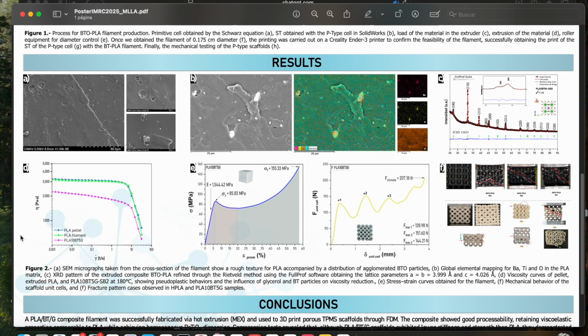The implications are that composition and architecture can be co-designed to target controlled failure in porous structures. For biomedical scaffolds, lightweight cores, or impact mitigation components, the PLA BTG TPMS delivers a practical balance: printability at low cost, tunable compliance, and enhanced energy absorption with predictable failure.